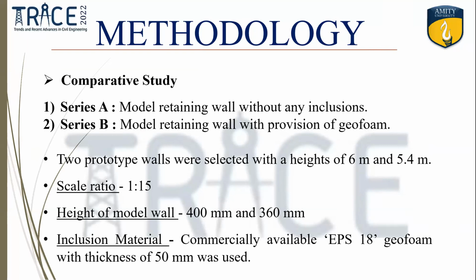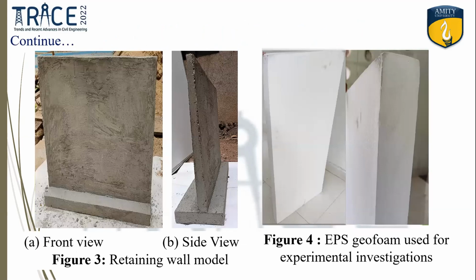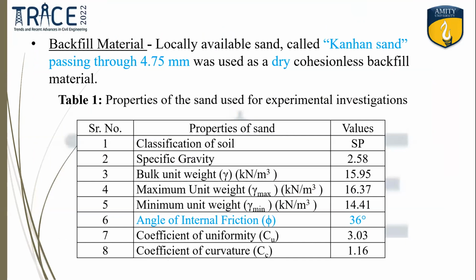Inclusion material which is used is EPS 18, with a thickness of 50 mm. Figure 3 shows the retaining wall model which is made up of cement mortar, and figure 4 shows the EPS geofoam material used for the study. The sand, which is called Kanhan sand, passing through the 4.75 mm sieve, is used as a dry cohesionless backfill in addition to the geofoam material. Table 1 shows the properties. This soil can be classified as a poorly graded sand, with specific gravity, bulk unit weight, angle of friction, coefficient of uniformity and coefficient of curvature as given.